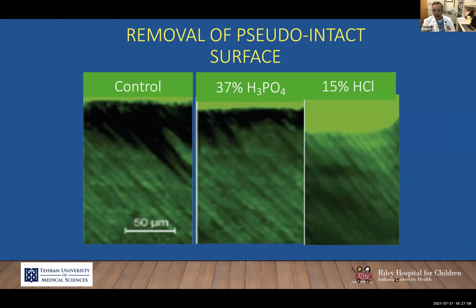Why do we use 15% hydrochloric acid rather than 37% orthophosphoric acid? The reason is that 15% hydrochloric acid is a lot more powerful. In other words, it is going to create much better mechanical retention, which we need. Remember, when we use resin infiltration, we are not providing any additional mechanical adhesion or preparation of the tooth, and this is interproximal. So the 15% hydrochloric acid that you see in this picture is going to cause more demineralization of the enamel and create bigger micropores that facilitate the adhesion of the infiltrant, which is the resin.